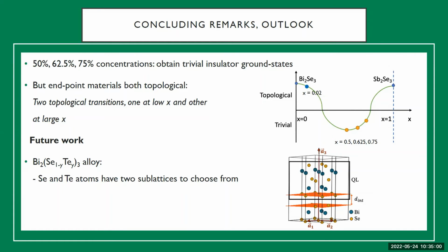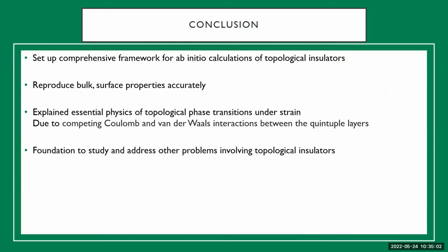But overall, what we were doing was trying to find different ways of tuning the topological properties of these materials, which is necessary for technologies which are based on these materials. So one of the ways that we were tuning the properties was strain, as I just mentioned. And then another way to tune the properties is through introducing disorder in these materials.